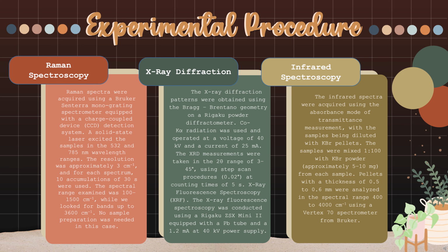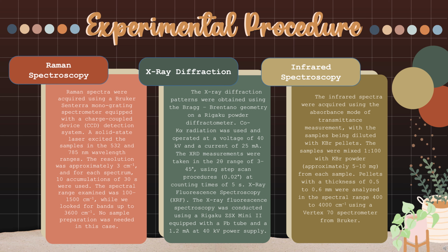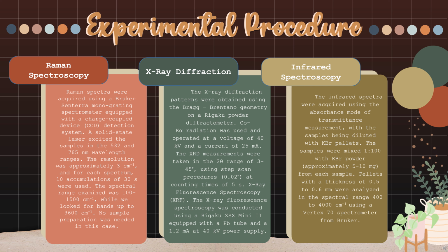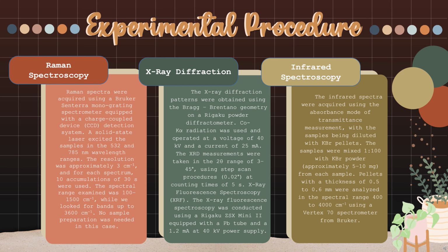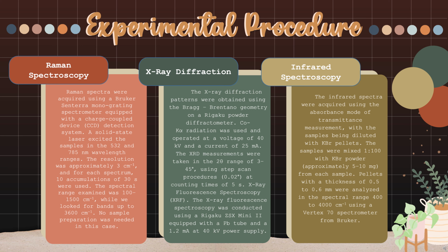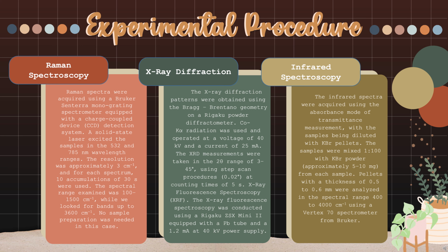In X-ray diffraction, CoK alpha radiation was used and operated at a voltage of 40 kilovolts and a current of 25 milliamps. The X-ray measurements were taken in the 2 theta range of 3 to 45 degrees using a step scan procedure and counting times of 5 seconds. X-ray fluorescence spectroscopy was conducted using a Rigaku ZSX Mini II with a Pd tube and a 1.2 milliamps at 40 kilovolts power supply.